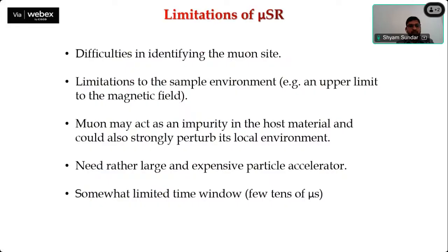So basically, we do these measurements at 2 Tesla or 3 Tesla, but when you keep applying a higher magnetic field, the experiment becomes more and more complicated in a technical aspect. And the muon may act as an impurity. Since the muon is an external particle going into your system, it can perturb its local environment, and then it can alter the intrinsic properties of your system. And so one has to be cautious.